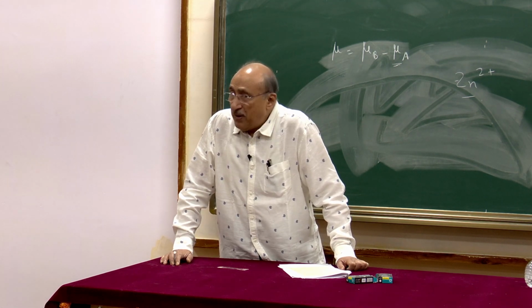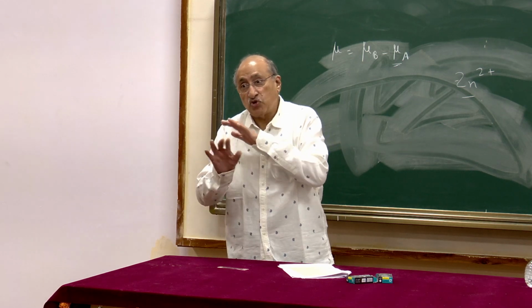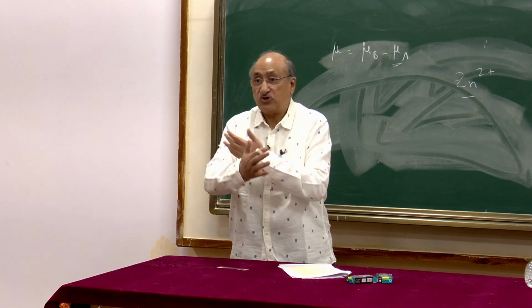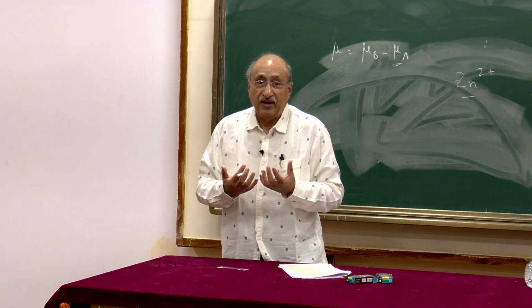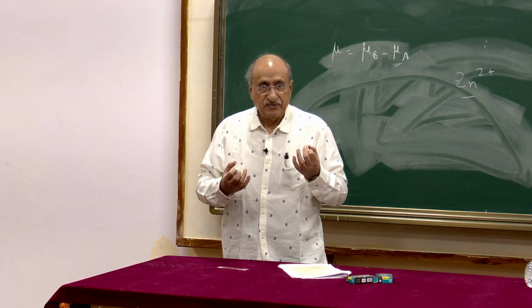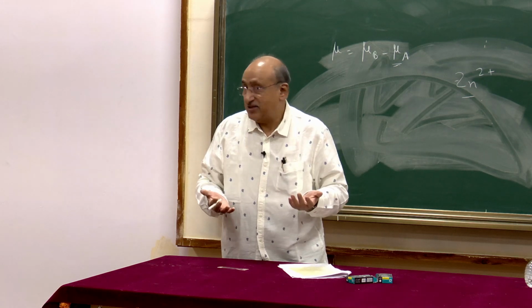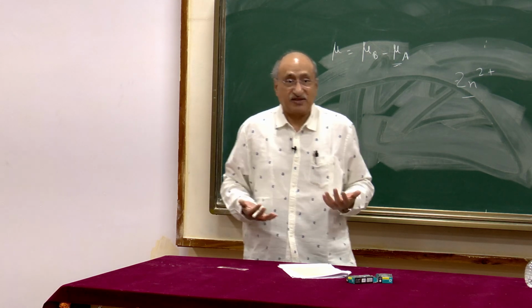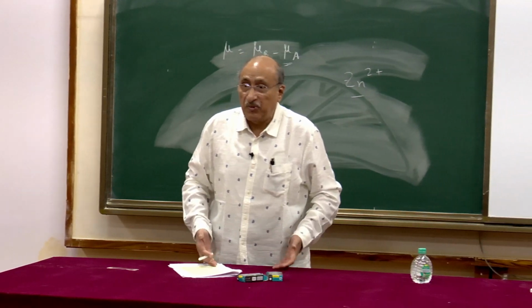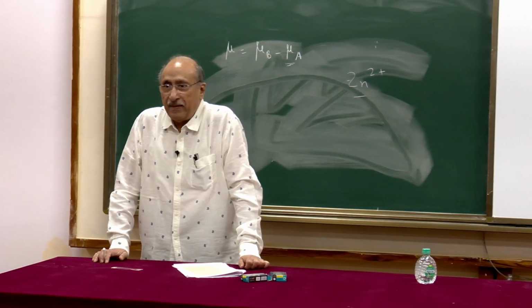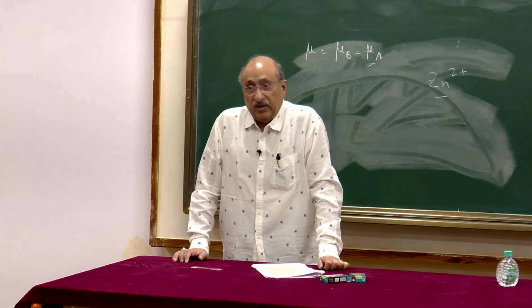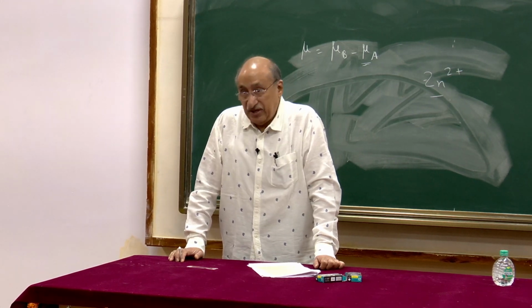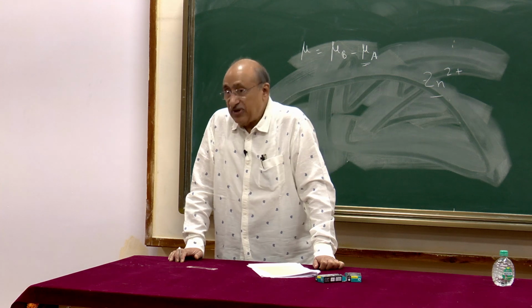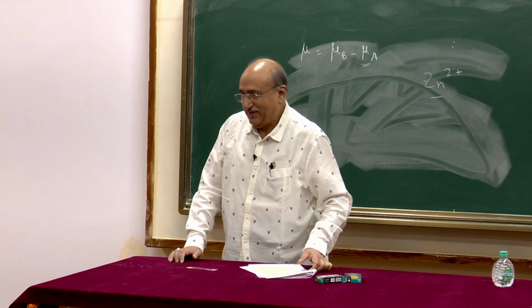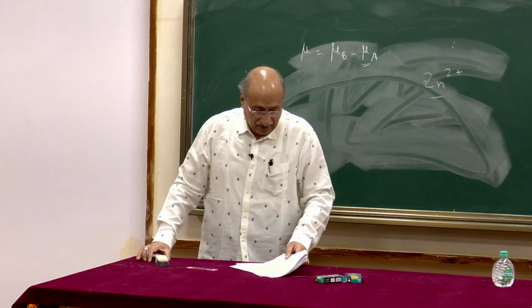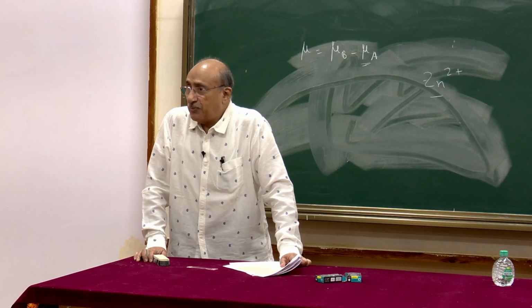But remember, many times enhancement of magnetic moment may not be suitable for the resistivity applications. So it depends again on the frequency, and what you really want, at what frequency you want your device to work. For example, garnet has a very low magnetization, that's what we discussed, but garnet has extremely high resistivity. So for microwave applications, many times people will prefer YIG, yttrium iron garnet, even though they are working with much lower magnetization, just because it has a higher resistivity. So again, it depends on your frequency of interest, where you would like to work.